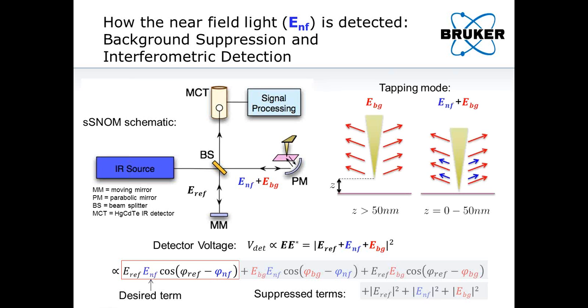The other way that you can isolate it is by employing tapping mode, for instance. So if you oscillate the tip, you're oscillating the separation distance between your point source and the sample surface. Therefore, you can reach a separation distance where you don't have any significant evanescent wave contribution to the scattered light of the tip.